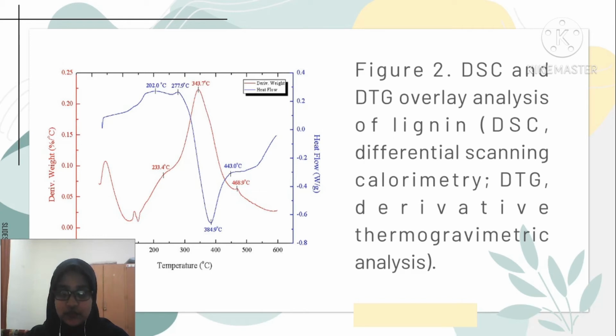To conclude, for the monosaccharide, an endothermic peak can be observed at 210 Celsius with a loss of mass peak at 230 Celsius. For the exothermic peak, the peak was observed at 330 Celsius with a loss of mass peak at 340 Celsius. Then, a slow heat release and slow loss of mass after 400 Celsius. For the cellulose, an endothermic peak was observed at greater than 335 Celsius, then it rapidly enters an exothermic stage, peaking at 378 Celsius, with a loss of mass peak starting at 380 Celsius and ending at 450 Celsius.